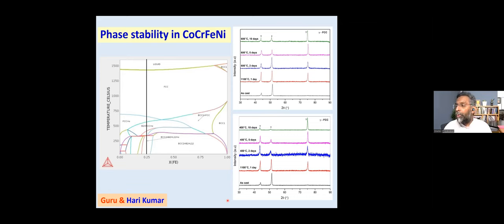So there is a need to develop phase diagrams. There are quite a number of people who are using computational tools to find out phase diagrams, and we have also done this. This is one such alloy, a four-component alloy. In the phase diagram, the y-axis is temperature and the x-axis is composition. My four-component alloy is marked by this black vertical line, which tells me the composition. Beyond a certain temperature, it is all liquid, and below that temperature it is a single phase FCC, until you come to a certain temperature below which there is a tendency for the formation of multiple phases. There is a tendency for segregation at low temperatures.